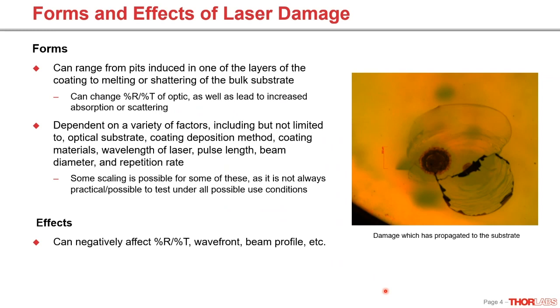As far as forms and effects of laser damage, this can range from pits induced in the coating to melting or shattering of the bulk substrate. And over here on the right, you can see that we got some damage to the coating, which propagated to the substrate. And you can see some cracking here. I mean, this almost looks like somebody's profile in that, here's the skull, here's a nose, and here's an eye. But as cool as these things sometimes look, we do prefer to avoid them.